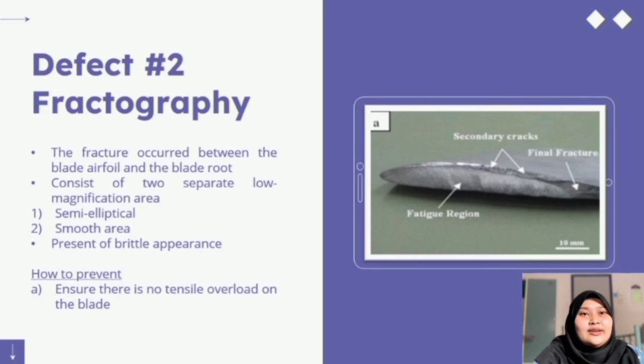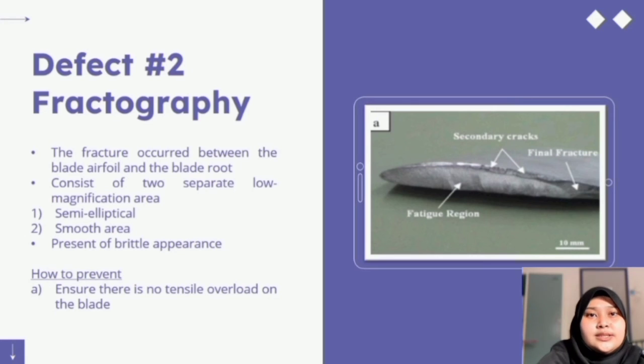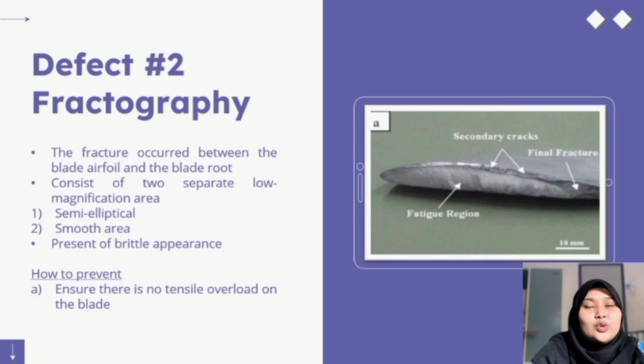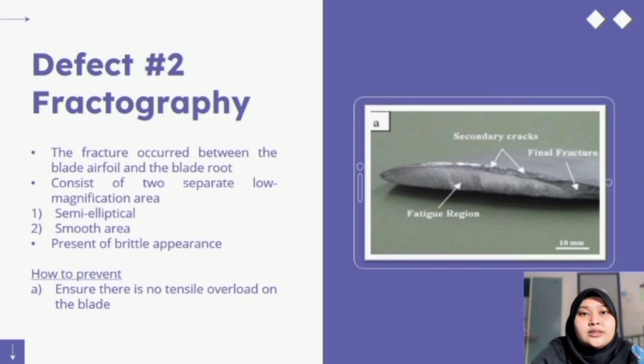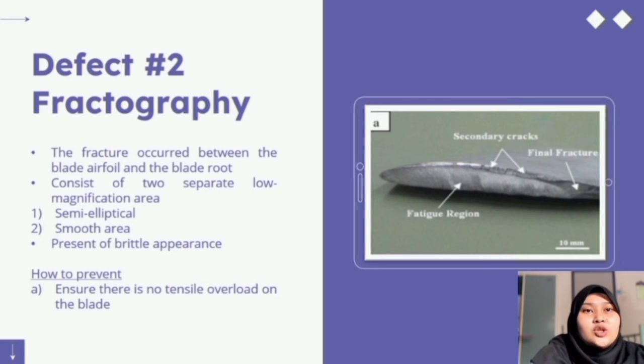Next, the fractography defect. Based on the picture, the fracture position of the broken blade can be identified. The fracture could be seen to have occurred between the blade airfoil and the blade root. The macroscopic properties of all the fracture surfaces were remarkably comparable. It is seen to consist of two separate low magnification areas: a semi-elliptical and smooth part that is normally oriented to the blade axis and presents a macroscopically brittle appearance, and a rougher and more ductile outer region. To overcome this problem, it is significant to ensure that there is no tensile overload on the blade.